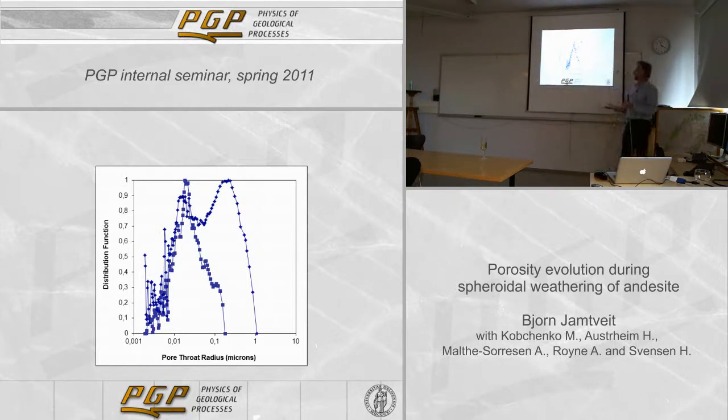And if you recalculate that to a pore size distribution, you would guess that the result would indicate that the altered rock actually has much bigger pores, or at least a fraction of pores much bigger than in the fresh rock. But we know from the CT scanning that this is not the case. So basically you just get a population of pore throats with higher radius, but not related to bigger pores. This is typically what you get during a fracturing process, where you get pores that are actually flat.